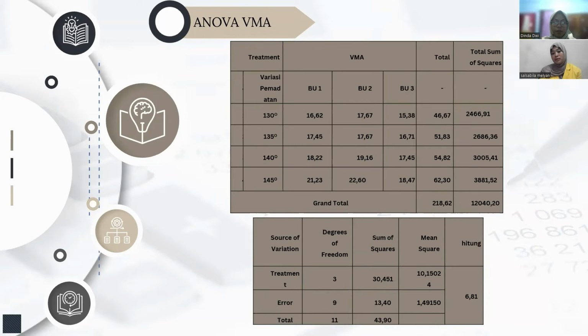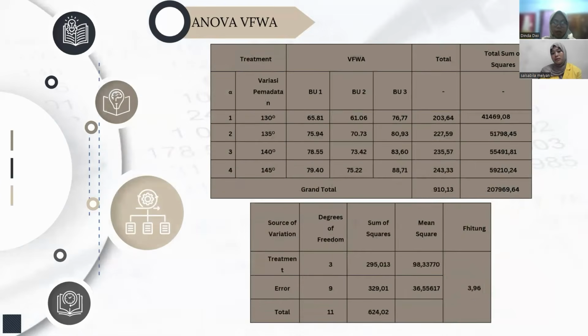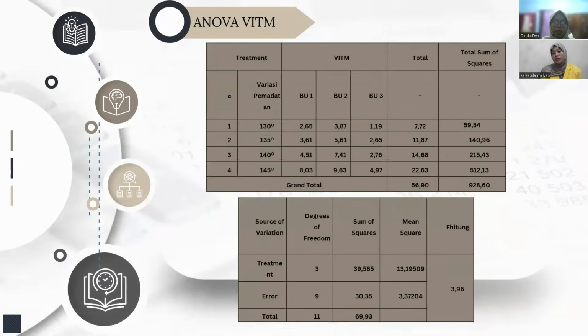The next parameter is VFA, voids filled with asphalt. This represents the percentage of voids in the mineral aggregate that are filled with asphalt. VFA has an F value of 3.96, as temperature improves asphalt penetration. Voids in total mix, VIM, represents the total air voids in the compacted asphalt mixture. VIM was 3.96. Temperature significantly influences total void content.